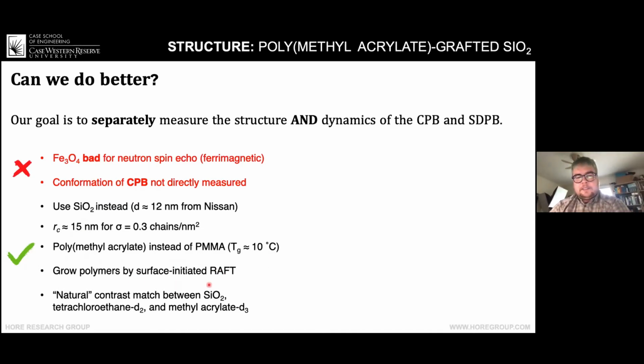We synthesize these polymers ourselves. And the system that we chose has natural contrast matching between silica, the solvent that we use, which is tetrachloroethane, and the methyl acrylate monomer when it's partially deuterated. And I'll speak a little bit about what I mean by contrast match in a second.